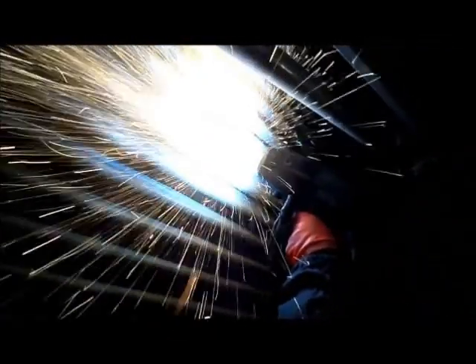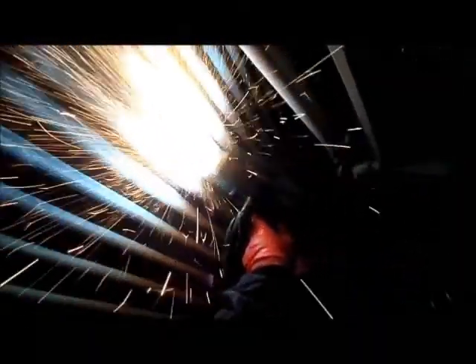The other is twin wire arc spraying, which uses twin wires, in that a wire becomes anode and the other becomes cathode. The two wires approach with electric voltage and make an electric arc within a short gap. The arc melts the wires and compressed air sprays it to the target surface. This is one of the most general processes in the field because the apparatus is relatively simple, but it makes high productivity with the best safety.